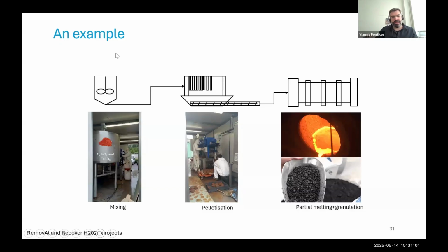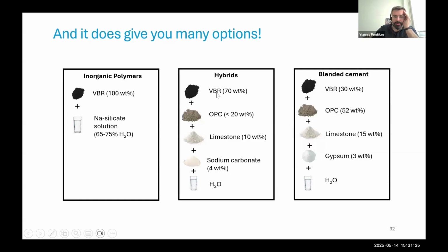Again, conceptually in the lab, and then you will also see it on a bigger scale, we have the mixing stage. This is a drum with a mixer, and here's a filter press that you see now from the other side. You create what we call our sausage, and your sausage is in fact your pellets that you can then melt, or use a rotary kiln or an EAF, we can discuss that, and eventually create the granules. What do you do afterwards?